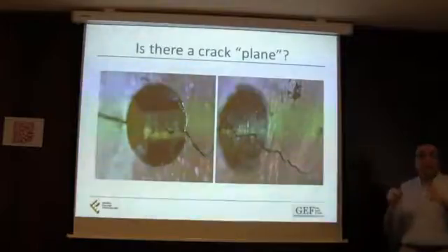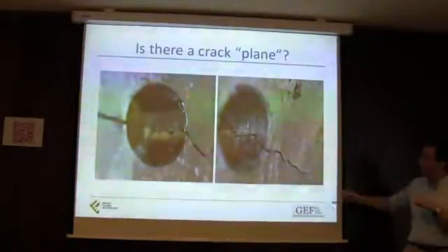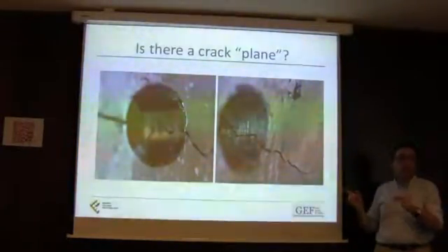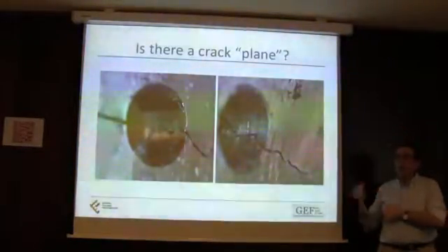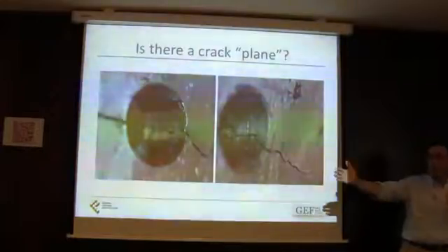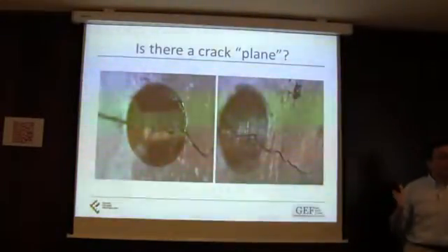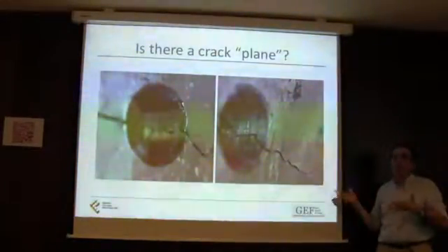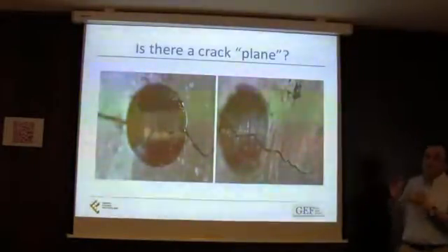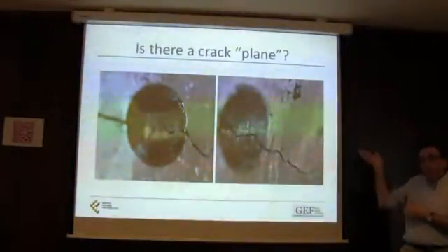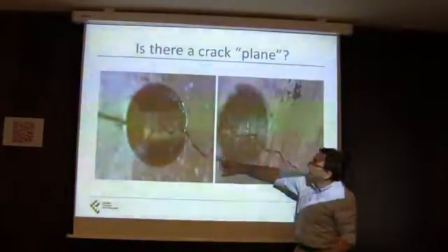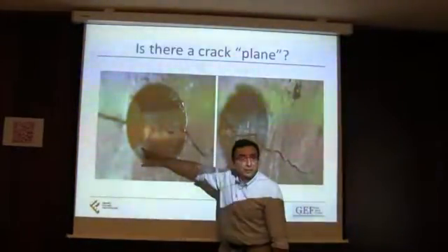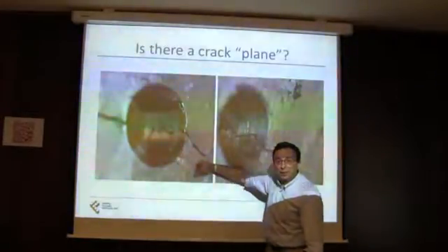Of course, these specimens are very thin, because some of them are 4 millimeters thick, and some are just 2 millimeters. And we have grains that go across the whole thickness of the specimen. So in this kind of situation, we would expect that the maximum shear stress plane would be inclined in that direction. So we were expecting this sort of thing, but certainly not this kind of thing here, right? It's really complicated. Okay.